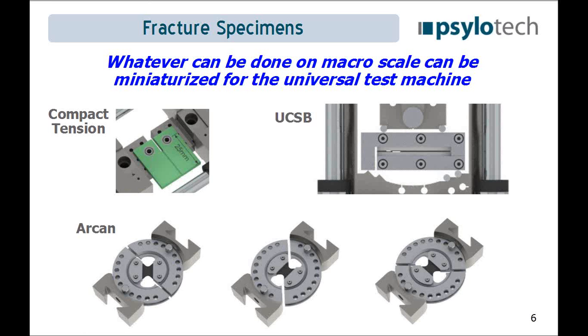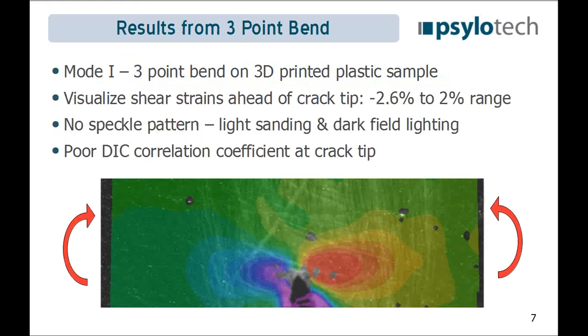But let me give a few example results. This is from a 3-point bend test. The center of this image is where the load was applied, and of course the outer sides were held as well. And it's really quite interesting to me. It surprised me when I saw this. With digital image correlation, you have to be careful about how you apply a speckle pattern. And we just tried this with a 3D printed plastic sample.